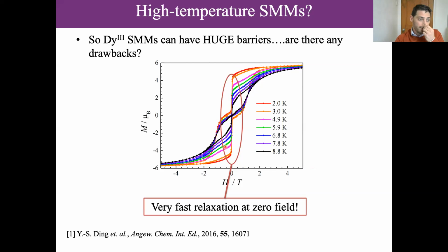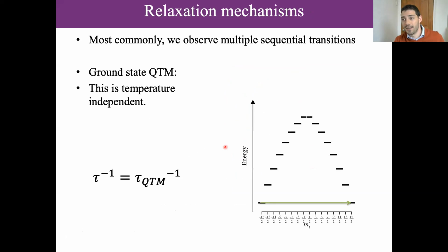And this is believed to be, or known quite well to be, quantum tunneling of the magnetization. This is an abrupt transition from one side of your energy barrier to another that was first identified for manganese 12. And this is temperature independent, broadly speaking, and is very efficient. So this is a resonant tunneling process. In many cases, we don't know whether it's coherent or incoherent, or exactly which states are involved, or what the role of phonons is. There are lots of questions for these kinds of materials at this point, which we need to study in detail, but it's a blight on this community.